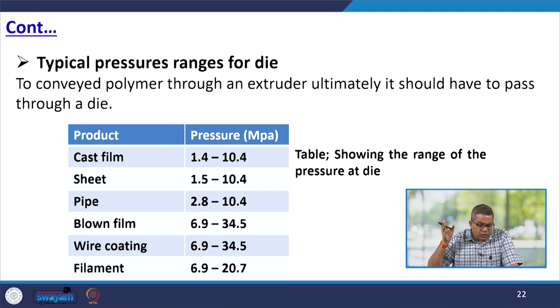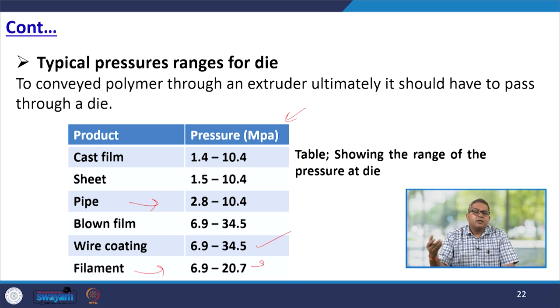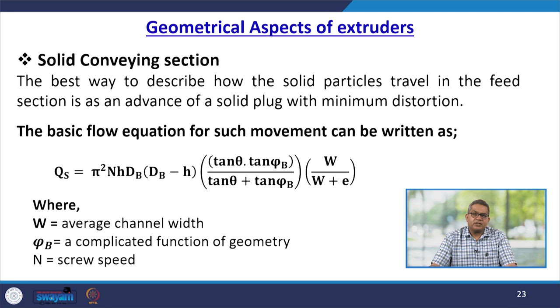Now, another crucial aspect is the typical pressure ranges for the die, because ultimately the melted polymer will flow through the die. To convey the polymer through an extruder, it has to pass through a die. Usually there are different types of products with listed pressures: cast film 1.4 to 10.4 megapascal, then sheet 1.5 to 10.4, then pipe, for which the usual process is the extruder, 2.8 to 10.4, then blown film 6.9 to 34.5, wire coating 6.9 to 34.5 megapascal, and filament 6.9 to 20.7. Now you see the variation, and this reflects how sensitive the products are towards pressure.